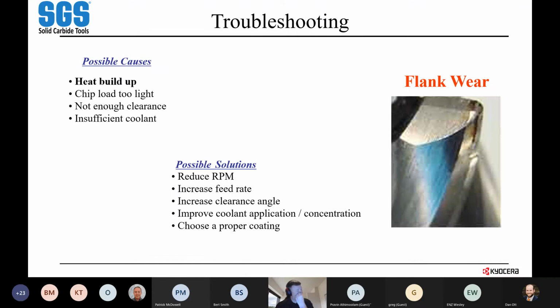Flank wear. Flank wear is almost always caused by heat buildup. That can be because you don't have a high enough chip load and the tool's just rubbing, or the geometry on the tool puts too much friction or contact with the part, or you just don't have coolant where it needs to be. But either way, all those boil down to heat buildup. So you can slow down your surface footage. You can try increasing your feed rate, get a heavier chip that's going to pull the heat away from the cut. You can look at some geometry changes with some more clearance.